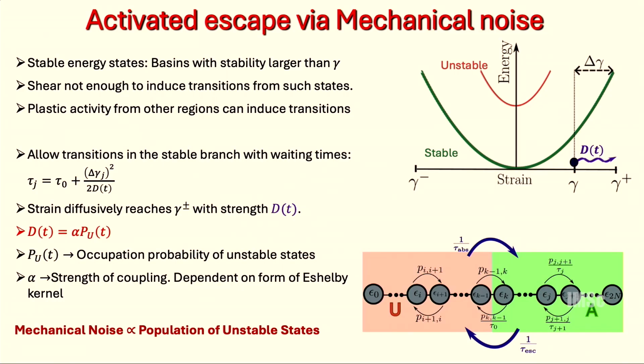So here is an illustration. If I'm sitting in a minimum like state like this, and this is my amplitude of strain, at this point I'm not quite at the stability limit. But if I imagine that because of stress kicks I diffuse in strain space, I can eventually reach that limit of stability and make a transition. Now, this diffusion in strain space, I would like to associate a diffusion coefficient to, and what I'm going to say is that this diffusion coefficient is going to be proportional to the fraction of states that are unstable to the given amplitude of strain.